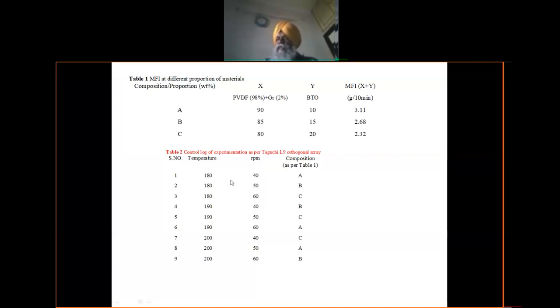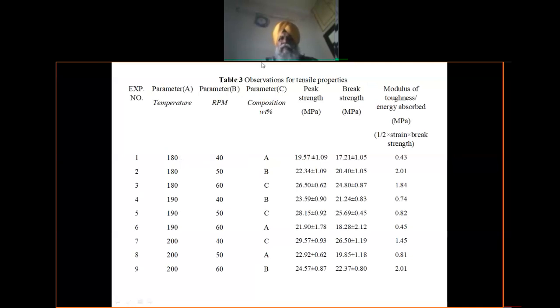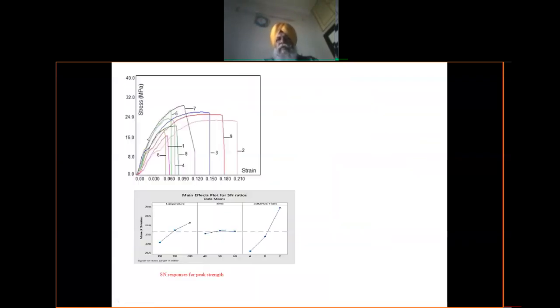Then we prepared, in a similar way, the feedstock filament by changing the temperature, by changing the RPM, and by changing the proportion of the material. And similarly, properties like the break strength, the peak strength, and the modulus of toughness were calculated. Right? How will we calculate? We will simply calculate the area under the curve. This is basically a test done as per the ASTM D638 standard. What this test says is, I prepare a dog bone shape component and hold it in the UTM, then I apply a tensile load, and these types of stress strain curves are developed, and we try to see what is the area under the curve.